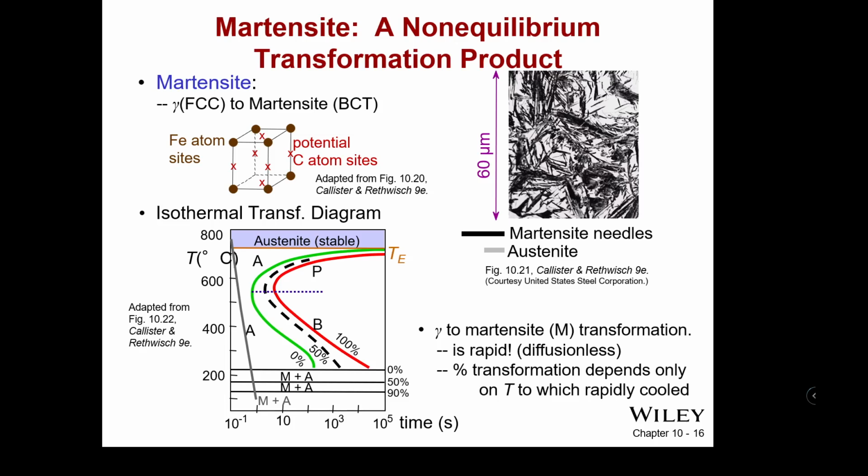The martensite is below the perlite and bainite temperatures. So you have to quickly, in a matter of less than 10 seconds, really only a couple of seconds, transition from the austenite region above 727 down below the threshold of about 220 or so, down below 220 C, to form a large percentage of martensite.